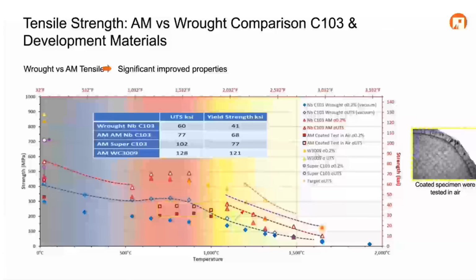And then another alloy, WC3009, which is another niobium-based alloy that has upwards of 30% hafnium in it. You can see here it charts out as an even higher strength alloy that is very printable. And then a material we're just starting to develop and put into use is our Castheon Super C103 material, with more data forthcoming.